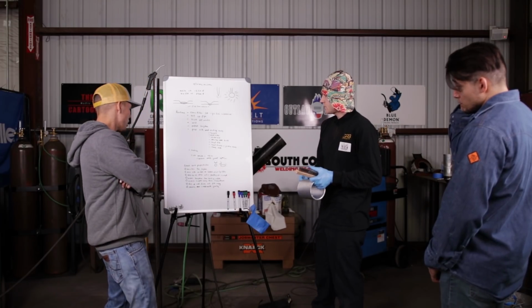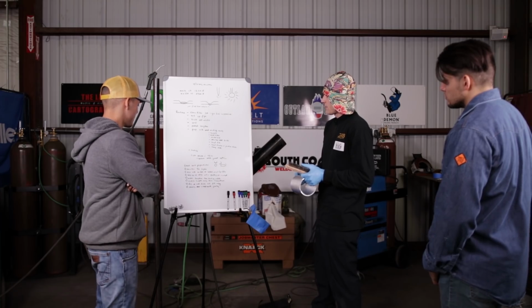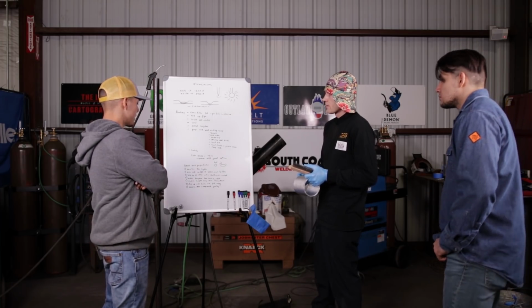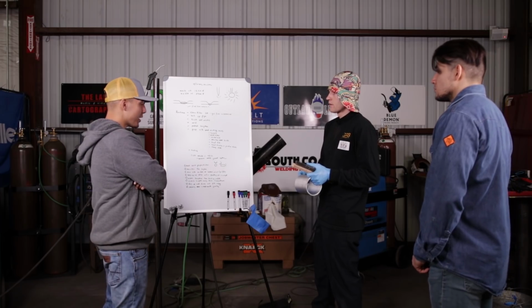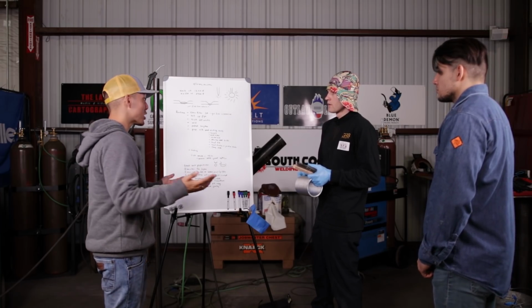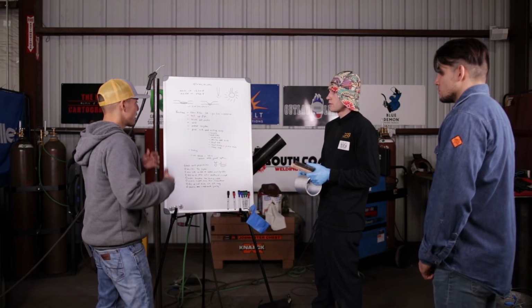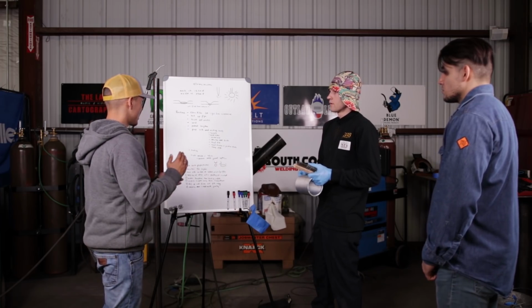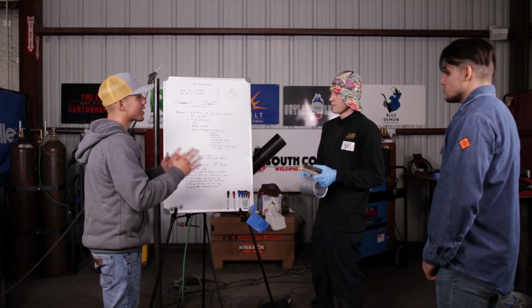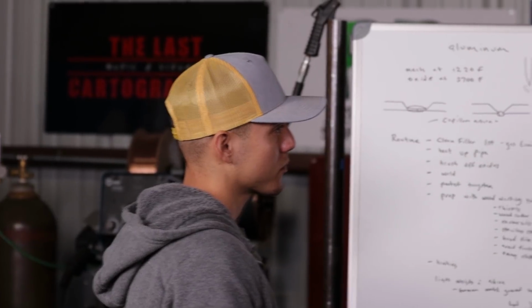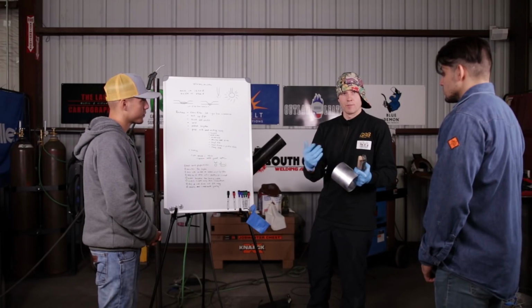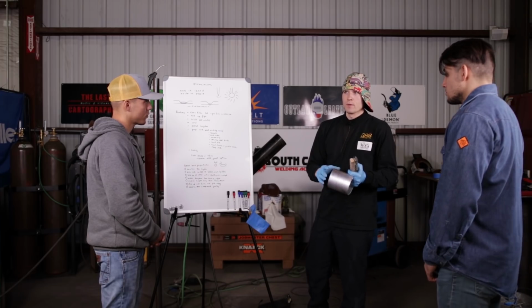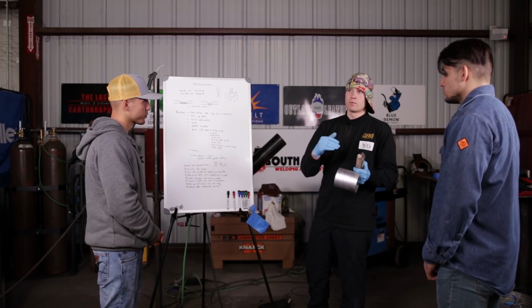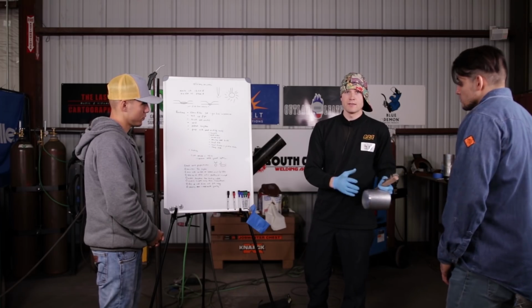Okay, sweet. So now, when it comes to aluminum, the settings on the machine, are you running AC or DC? Let these people know, especially because, like I said, it's an introduction to aluminum. Even though we're doing an open root pipe, the machine we're using is a Miller Dynasty 350. What's a recommended machine for aluminum? Essentially, as long as you have a machine that is AC capable, with the negative for the welding characteristics and the positive for the cleaning action,